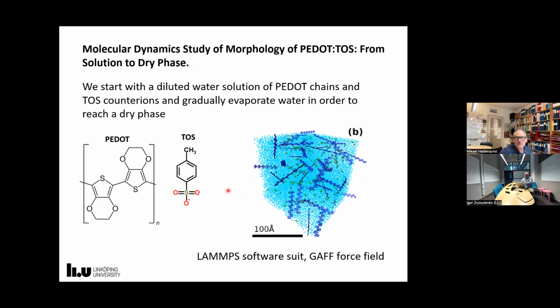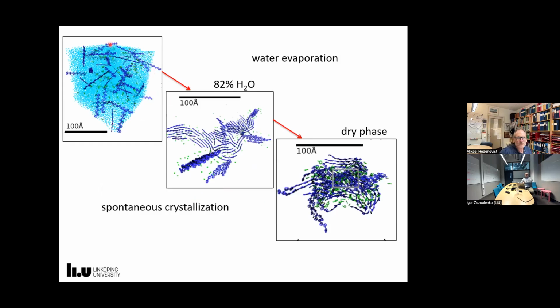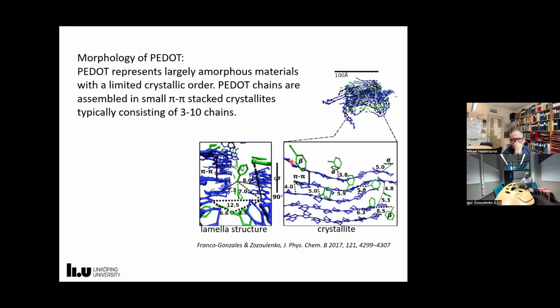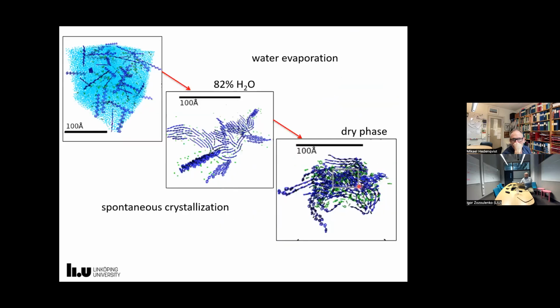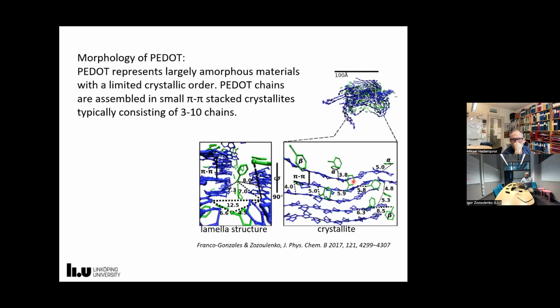This is what we are doing here. And basically, you start with this computational box, put a lot of water here, and you mimic a real process of synthesizing PEDOT thin films. And then you evaporate water, and finally you arrive at a thin film, which looks like this in the dry phase. So basically, what you see here is that PEDOT, as many other conducting polymers, is essentially an amorphous material with some limited crystalline order. So here you see some crystallites.